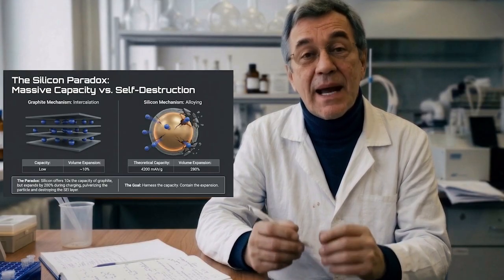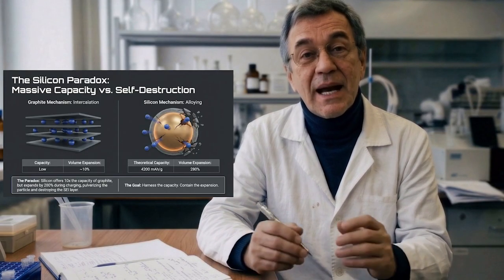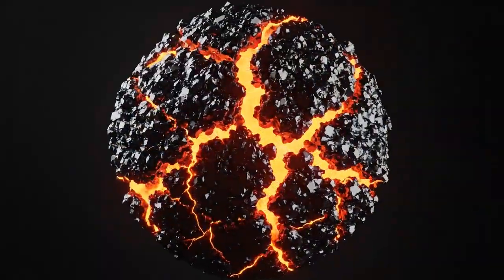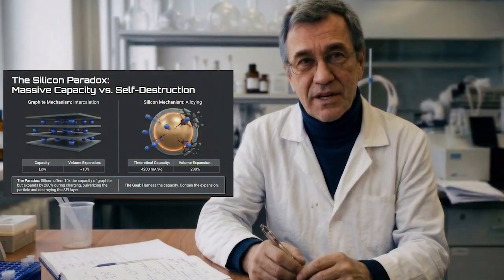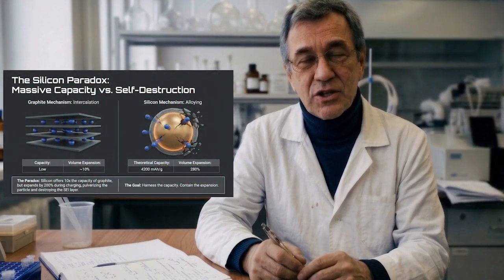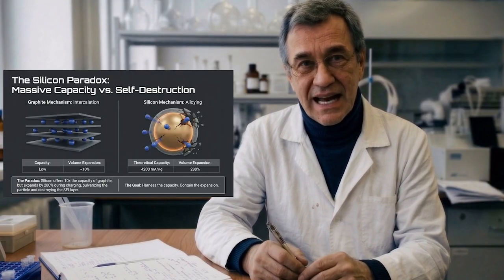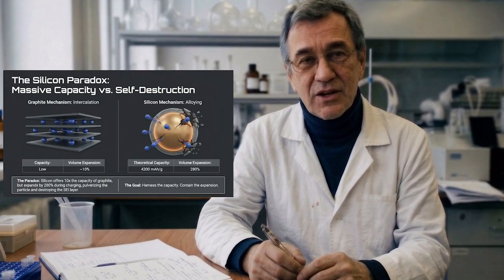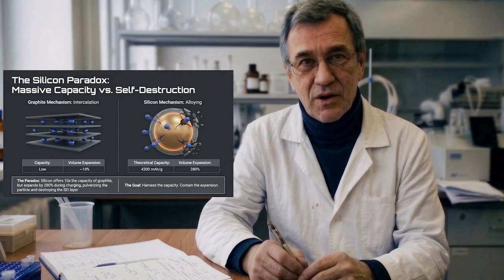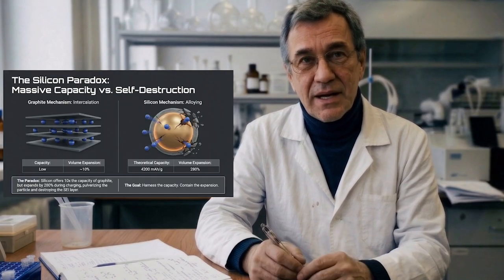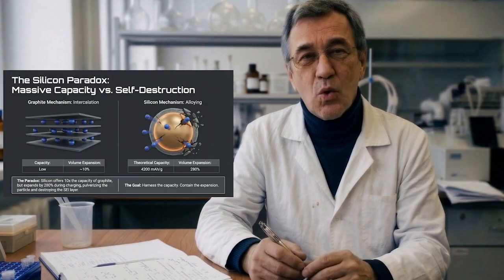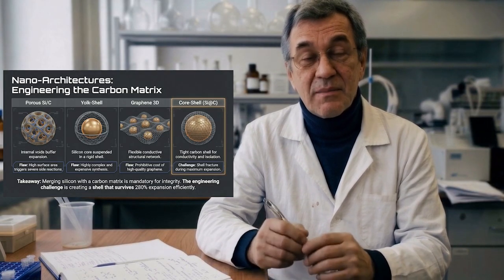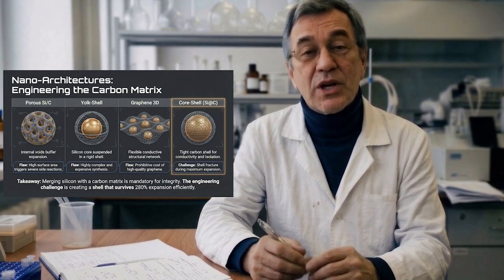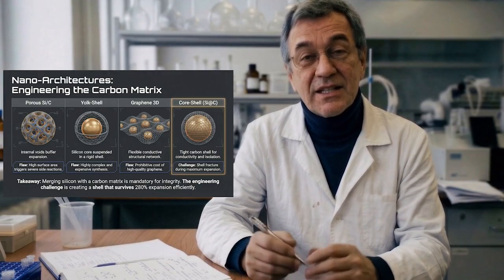But there's a problem, and it's a big one. While graphite gently expands, silicon undergoes a violent transformation. When it absorbs lithium, it expands by a staggering 280%, forming a brittle alloy. This massive volume change pulverizes the silicon particles, shatters the delicate SEI layer, and consumes the electrolyte, leading to rapid battery failure. The industry has been forced to either limit silicon content to small fractions or rely on complex, expensive manufacturing techniques. The core challenge, therefore, is to stabilize silicon.